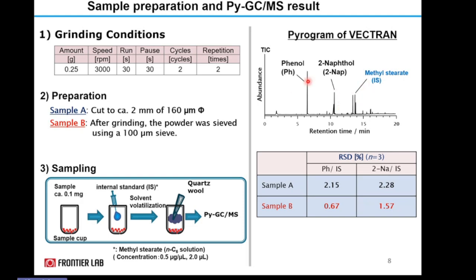Just to see the reproducibility between the fiber and the powdered sample, we have compared the ratio of phenol and naphthol over the internal standard methyl stearate. For sample A, I think you get around 2%, 2.15 and 2.28. Whereas for sample B, which is after grinding, the powder gives a much better reproducibility. In terms of RSD percentage, RSD is less than 1% for phenol and slightly over 1% for naphthol. So in short, the powder sample gives better reproducibility than analyzing the fiber sample directly. That's the point we try to convey through these experimental results.